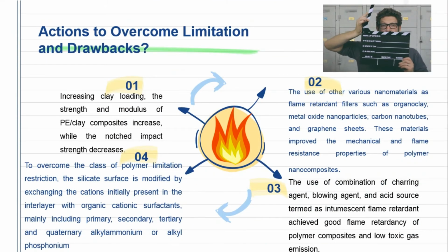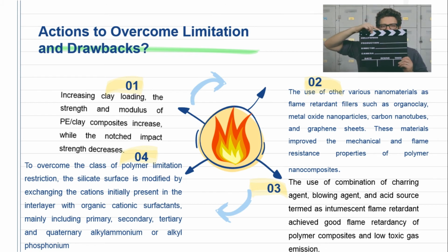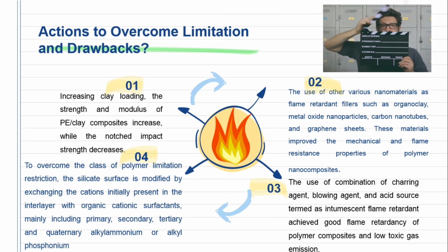Next, the actions to overcome limitation and drawbacks. So first, increasing the clay loading, the strength and modulus of PE clay composite increase while the notch impact strength decreases. Second, the use of other various nanomaterials as flame retardant fillers such as organoclay, metal oxide nanoparticles, carbon nanotubes, and graphene sheets. These materials improve the mechanical and flame-resistant properties of polymer nanocomposites.